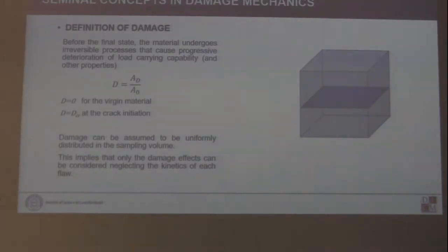The second seminal concept in damage mechanics is the definition of damage. Before a final fracture, the material undergoes an irreversible process that degrades or reduces the material properties and reduces the load carrying capabilities. If we assume that the damage is isotropic in a reference volume element, we have a variable which is defined as the ratio between the damage area over the nominal resisting area.